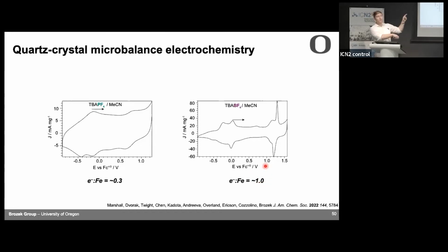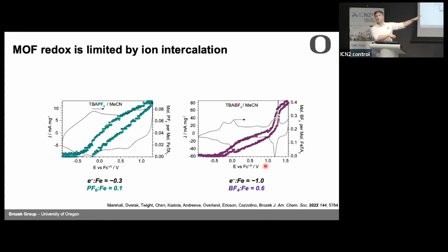But at the same time, you can watch the change in the mass. And so in both cases, the mass increases as you oxidize the material. That's consistent with the anions going inside. So they increase in both cases, so that's good. But the biggest mass increase happens at that potential, at that feature that was really, really positive and really sharp.